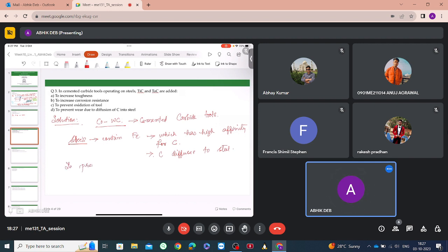To prevent this, titanium carbide and tantalum carbide are added, because these compounds, in contrast to tungsten carbide, have very high affinity for keeping the carbon with themselves. So the addition of these will prevent the diffusion of carbon atoms to the steel. As a result, the strength and hardness of cemented carbide tools can be maintained during machining of steel.